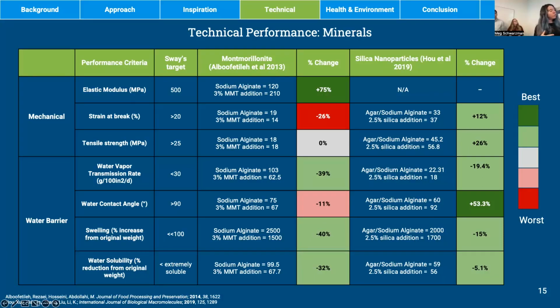So both materials show significant improvements from the baseline, notably with respect to the water barrier. And it's also worth noting that while only the silica nanoparticles increase the water contact angle, while montmorillonite actually decreases it, both materials still improve the overall water vapor transmission rate, which is the more important consideration here.